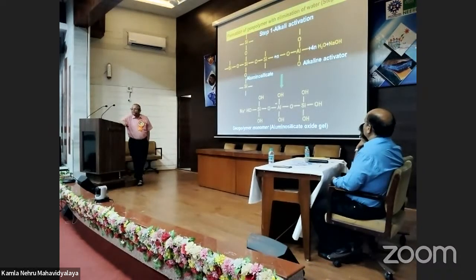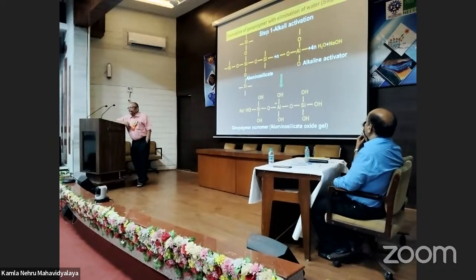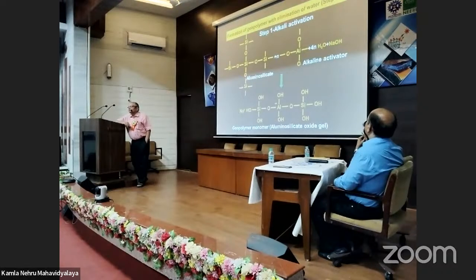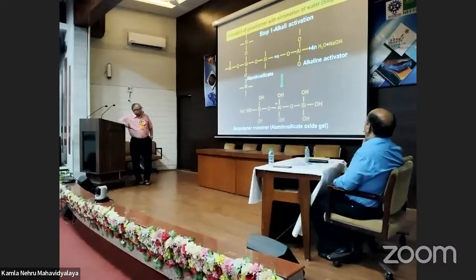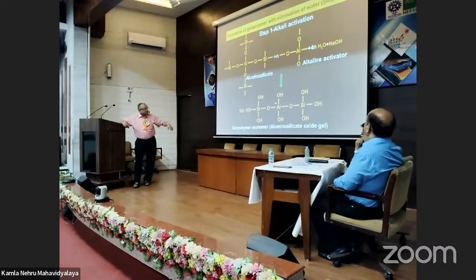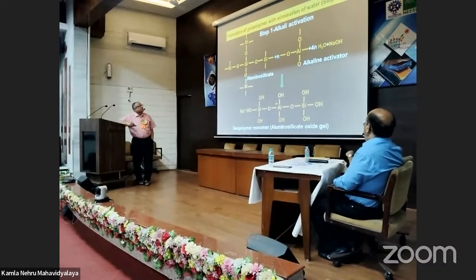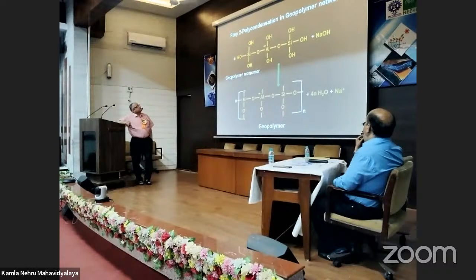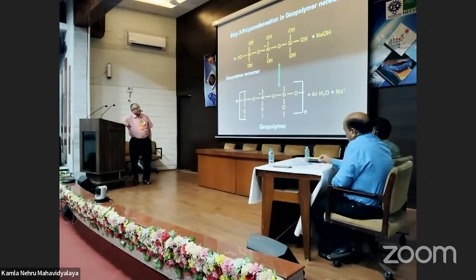Now, these are the chemical species, how the geopolymerization or the polymerization takes place when you mix the raw materials, fly ash or slag with sodium hydroxide and sodium silicate. Here you have the aluminum silicate structure, and you have water and sodium hydroxide, alkaline activator. And when you mix it and homogenize it, you get geopolymer monomer, that is aluminum silicate oxide gel. This geopolymer gel further reacts with sodium hydroxide in the presence of sodium silicate, forms a geopolymer backbone, and